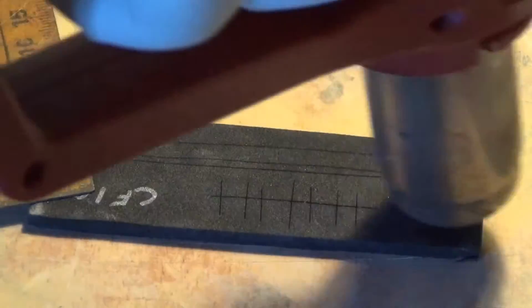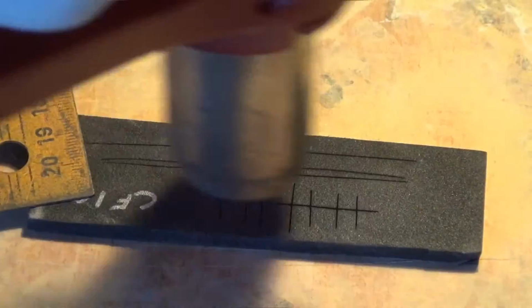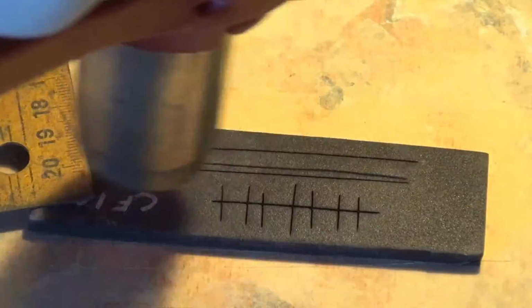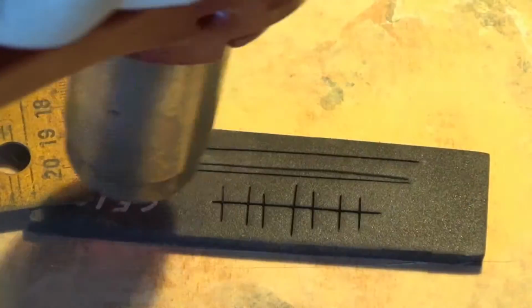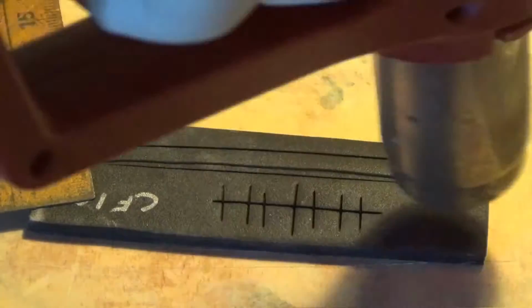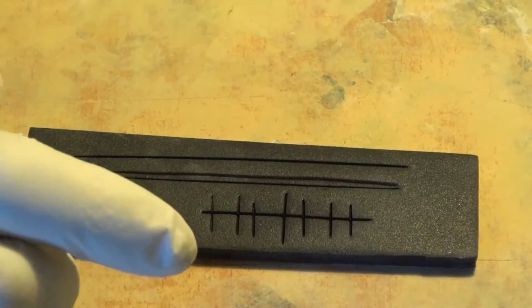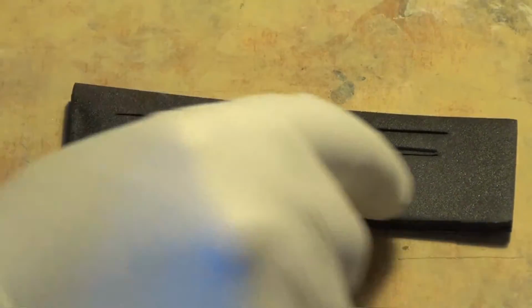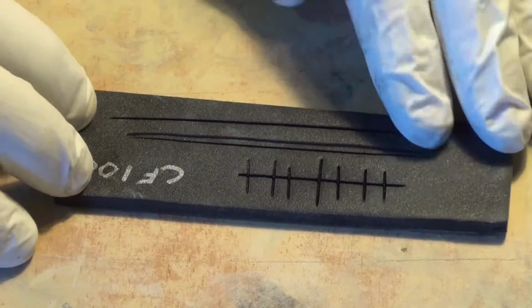On the CF100 sample, heating it with the hot air gun has an interesting effect. The half cuts will open slightly, about half a millimeter to each side in all the depth of the cut, which can allow the adding of some interesting and intricate details to the pieces.